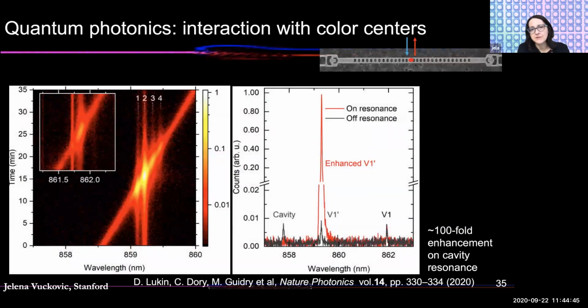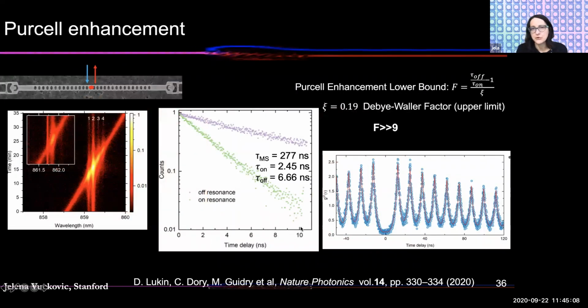So that's nonlinearity in silicon carbide. Again, going back to quantum optics, you can put everything together, these high quality photonics together with quantum emitters. We've demonstrated a large enhancement of emission from color center, silicon vacancy color center embedded in silicon carbide resonator, a larger than 100-fold enhancement on resonance with the cavity. Of course, we have also shown that all of that has been done for a single emitter based on second order correlation measurements. And in this case, the measurements were done on this V1 color center because of the orientation of the dipole relative to the cavity, but we're at the moment working primarily with V2 color centers.